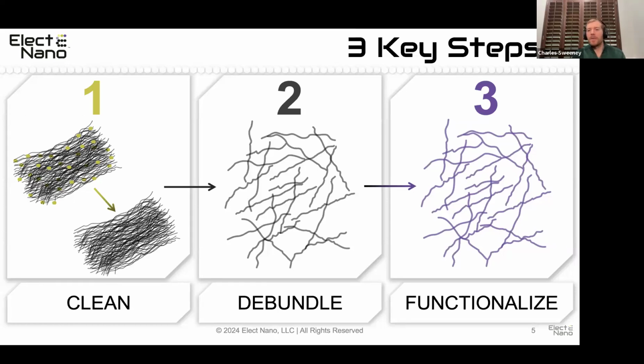But it's really a way that we've developed to disentangle the carbon nanotubes, separate them out without breaking them into little pieces. So we're not taking a super high power probe sonicator and just beating them to death until they're little tiny chunks of carbon nanotubes. Our company has figured out and patented ways to disentangle the nanotubes gently, but very efficiently. So we matched the process to the type of shear and entanglement that we see in the nanotubes to begin with. Step 3, we functionalize.